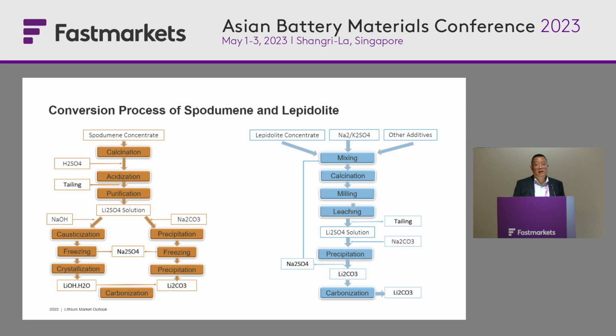By carbonization, it means you have, say, 98% or 99% carbonate. You mix the carbonate with water, okay, and you continuously add carbon dioxide. And then what you will get is lithium bicarbonate, LiHCO3. And then this stuff is not stable. You heat it again, it will change back to lithium carbonate with higher purity. And the impurities like sodium, potassium, and so on will stay in the solution. So basically that's the process, okay? Again, I'm very commercial, so you can ask me and you can challenge me if I have something wrong.